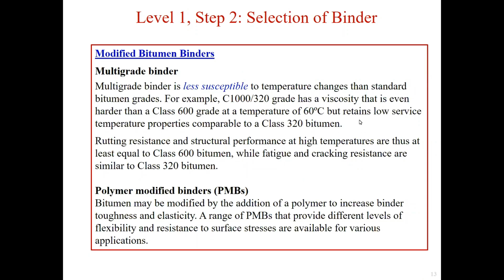Now let's look at the modified bitumen binder. Compared to standard bitumen grades, the multi-grade bitumen is less susceptible to temperature change, so it can provide improved deformation resistance at high surface temperature, while retaining the desired level of flexibility at low temperature.